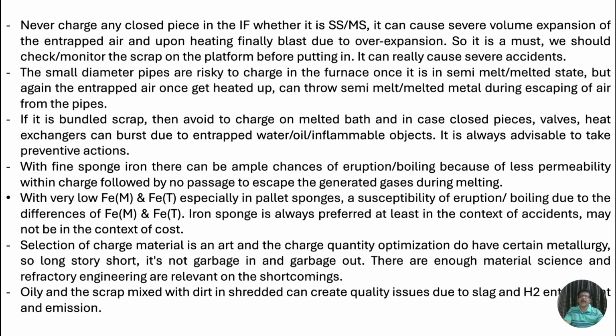With fine sponge iron, there can be ample chances of eruption or boiling because of less permeability within the charge, followed by no passage to escape the gases generated during melting. With very low FeM and FeT, especially in pellet sponges, there is a susceptibility to eruption and boiling due to the differences of FeM and FeT. Lump sponge iron is always preferred, at least in the context of accidents, may not be in the context of cost. Selection of charge material is an art, and charge quantity optimization does have a certain methodology.